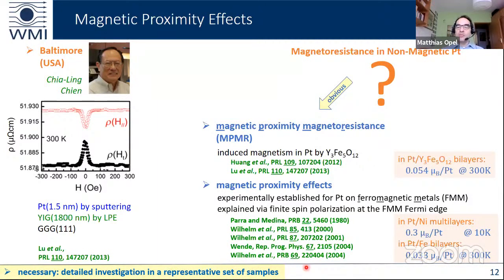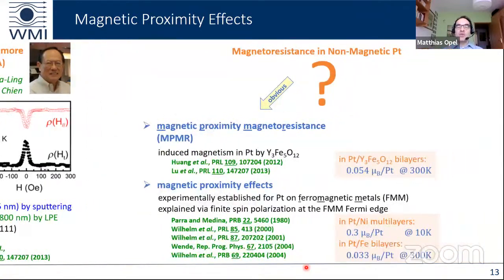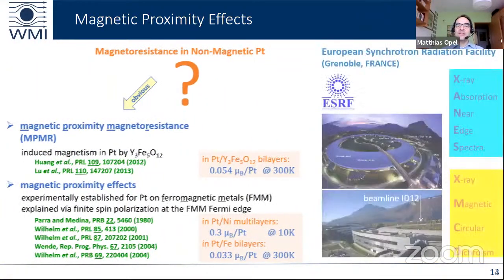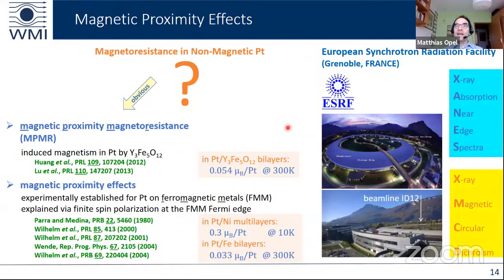So we prepared a representative set of samples to investigate this magnetoresistance in non-magnetic platinum via an element-specific technique. And we took the samples to the European Synchrotron Radiation Facility in Grenoble in France. There, we were able to measure element selective the X-ray absorption near edge spectra at the energy of the platinum edge, and we were able to measure the X-ray magnetic circular dichroism also at the platinum edge.